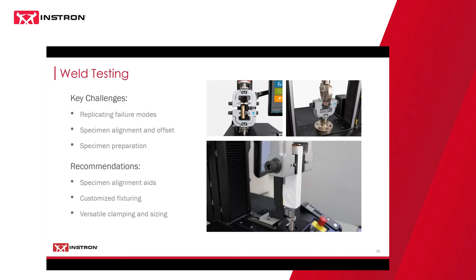Some welds need to maintain a true 90 degree angle throughout the entire test, whereas other welds just need an offset, or they don't need to maintain any angle. It's more of just a grip it and rip it type of weld. But you need to ensure that you know the failure mode that needs to occur. You need to understand how maintaining 90 degrees versus just pulling and ripping it will affect the results. So ensuring proper alignment is also very critical here. Ensure you're setting up and running each test comparably for the most repeatable results.